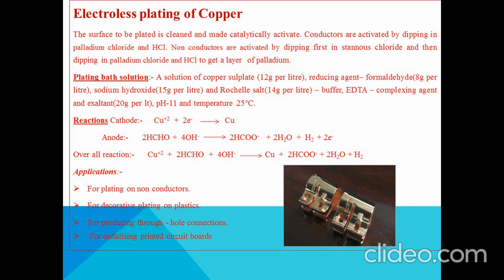The plating bath also contains EDTA, which is a complexing agent and exaltant, that is 20 gram per liter of the solution. EDTA, being a complexing agent and exaltant, means the complexing agent will react with the metal ion to form a complex compound, thereby reducing its concentration in the solution in order to get a thin and good deposit. Exaltant will increase the rate of the reaction. The pH of the plating bath is maintained at 11 and temperature at 25 degrees Celsius.